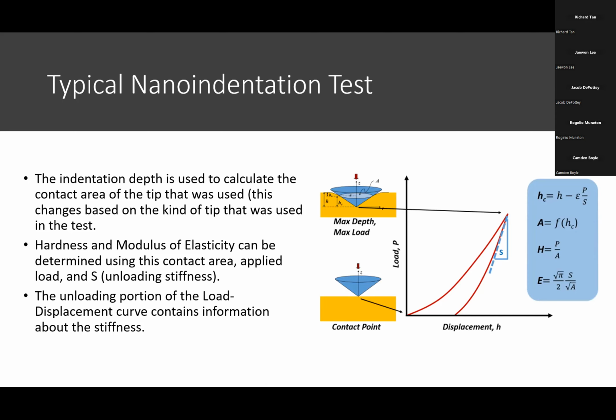You find the hardness with tests like this: it's your loading pressure divided by your area. And things like Young's modulus right here is in relation with the square root of pi divided by 2, times the unloading stiffness divided by the square root of the area. Here there's a sample graph of your load and displacement of this arbitrary indentation test, and the slope of that line is your unloading stiffness.